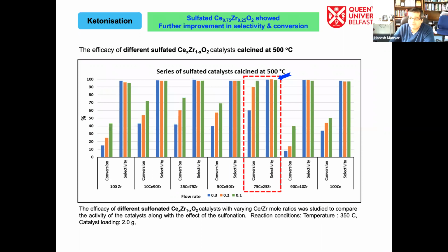And in this case, we did the sulfation of the mixed metal oxide catalyst as well. So these are the optimized results. There have been a number of different optimization studies in terms of the composition of the materials, the precursor studies, the techniques for precipitation, and different optimization of the concentration of the sulfation. But they all have been done and taken care of. And the end result, the optimized result, is that we can achieve very high conversion and very high selectivities close to 100%, nearly 96% conversion with 98-99% selectivity to the desired ketones through sulfated ceria zirconia type catalytic materials.